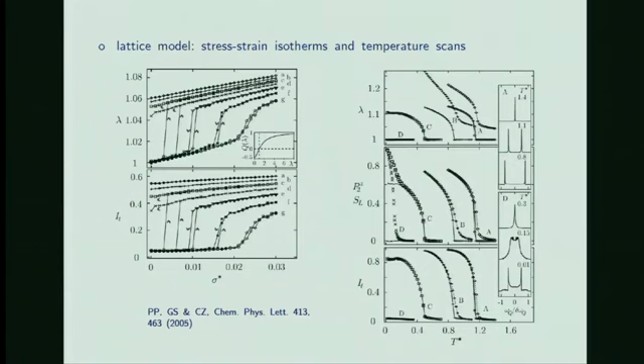Okay, then we also did temperature scans. For example, for a regular sample with all epsilon interactions positive, we have similar curves as in the Gay-Berne case, like here, and looking at P2, a similar story can be seen. And we also looked at NMR, single peak, double peak, and then one can also play with these epsilon ij constants in the Lebwohl-Lasher terms.